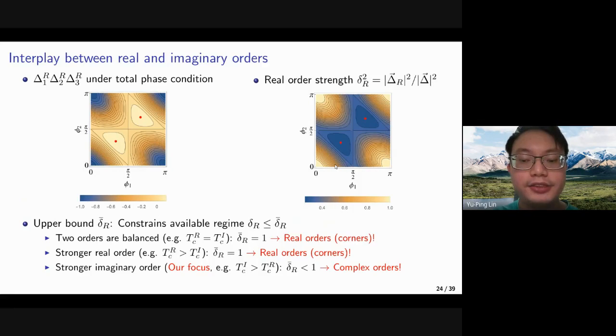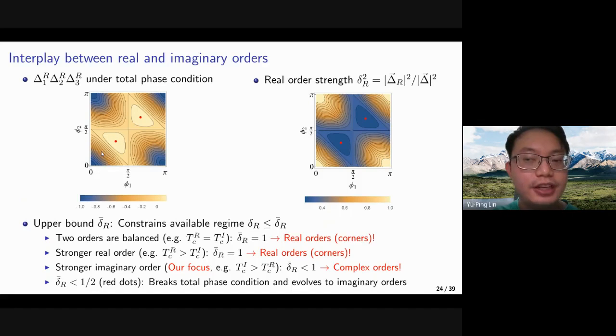So we could characterize the degenerate ground state at each real order strength by the energy contour in the free energy phase diagram. If we are pushed further so that the upper bound is lower than the minimum of the real order strength here, which are the red dots, we are breaking the total phase condition because it is not compatible with the total phase condition now. And if it becomes lower, we will evolve continuously to the purely imaginary order, where the delta R upper bound will vanish at the end. So this is the phase diagram that we're going to look at.